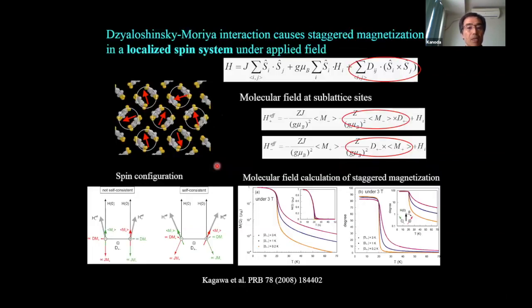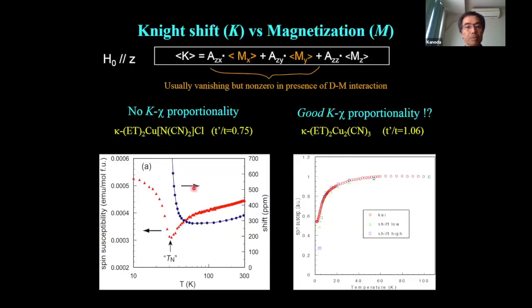In such a kappa-type molecular arrangement, it is very reasonable that the Dzyaloshinskii-Moriya interactions give no K-chi proportionality. However, please take a look at the right-hand side figure. This is the spin susceptibility indicated by red open circles, and the Knight shift, which is the blue or green symbols. It's invisible, I'm sorry. But anyway, these two quantities are mutually scaled. This is very funny. This is very strange.